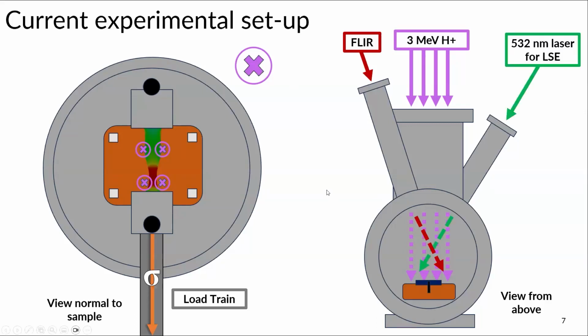And then for the strain tracking, we have the capability to do in situ strain tracking. So I roughen my sample surface with 4,000 grit sandpaper so that it creates a variable topography. We shine a 532 nanometer green laser at that surface. When it's reflected back into the camera, it creates a black and white contrast in which we can have specific areas of interest circled on our sample, and then we can track the strain that way. So we can track localized strain throughout the entirety of my experiments.